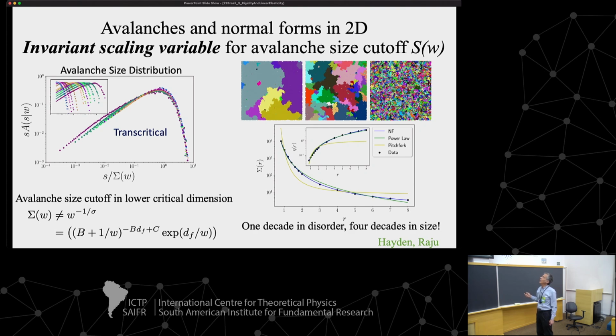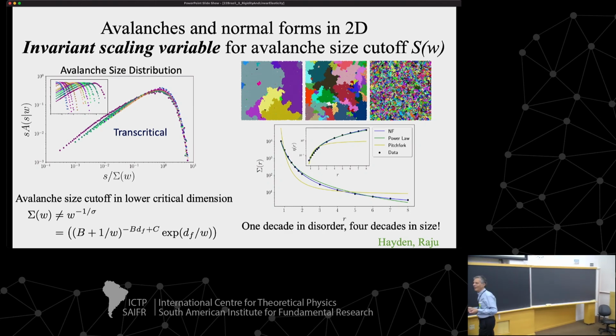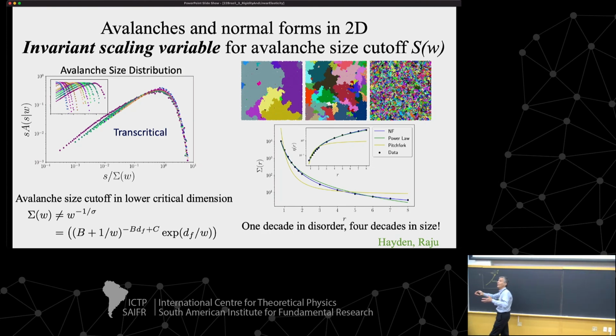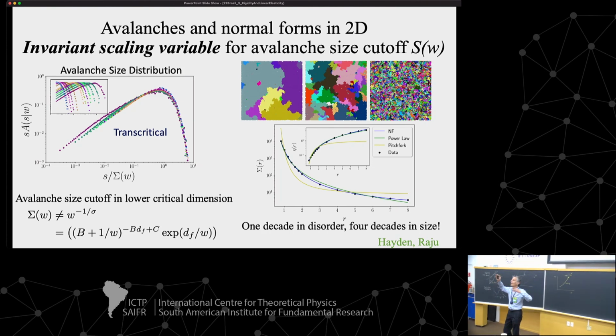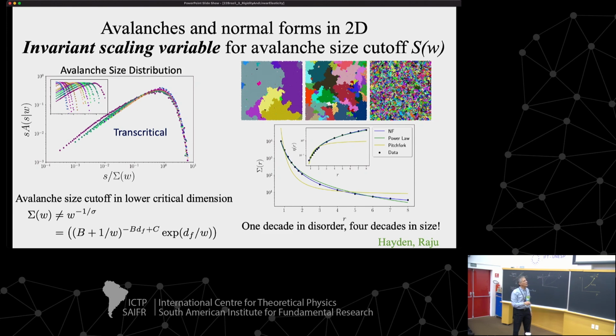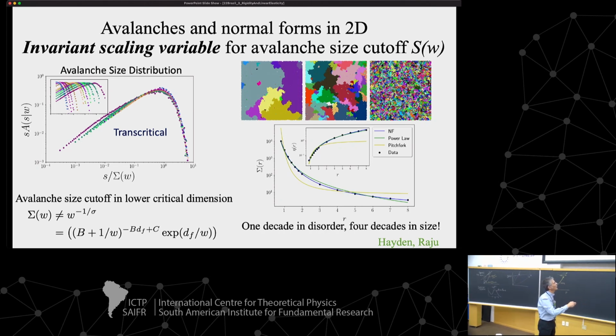Previous people would do simulations like this, but on a square lattice. On the square lattice, if you zoom in here, these bumpy regions have long facets. They were driving us crazy and everyone else has been suffering from them. And so they would do bigger and bigger simulations where the facets maybe got a little less important, and they would find that they could fit all their data with a power law. So here's a power law fit like the ordinary one, and that green curve is clearly not as good as our blue curve.